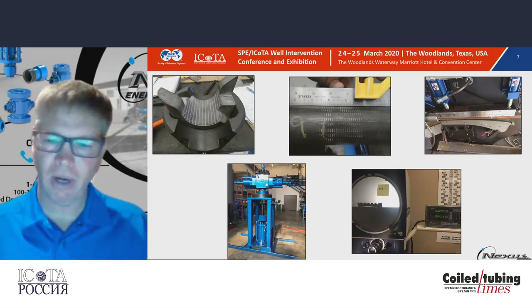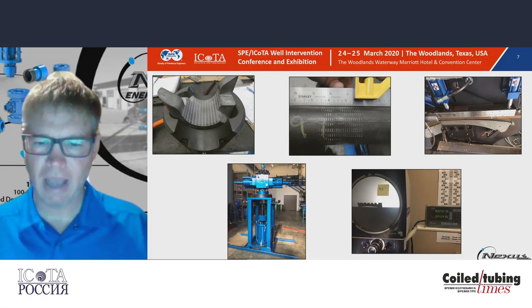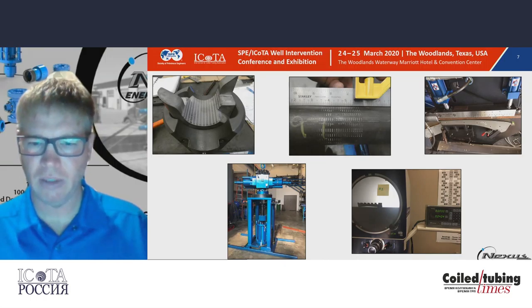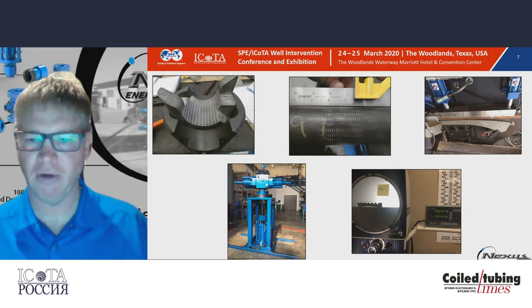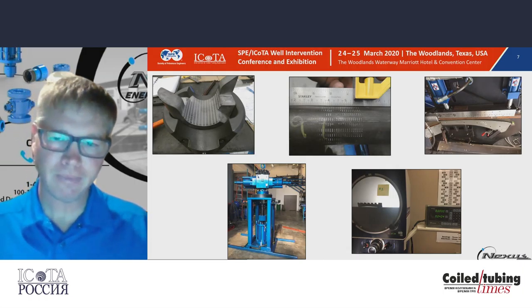And then the picture on the bottom right is an image of our optical comparator. We applied metrology putty, like a mastic putty, to the slip marks, and we let it harden or cure. Then we removed that and sectioned it, and we put it on the optical comparator. That allows us to measure the depth of the slip marks, indirectly, but it's a very accurate way to do that.